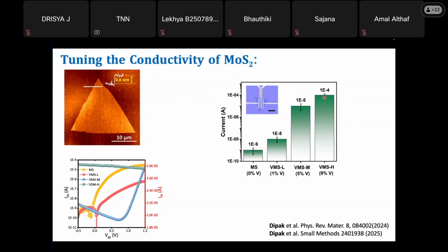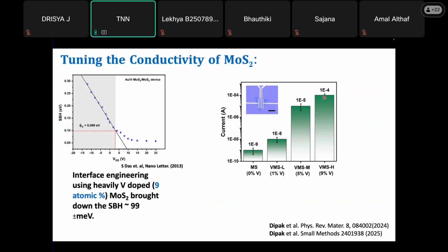Now the interesting property is that when we bring this contact to the metal-semiconductor, the MoS2-gold contact, we could bring down the barrier to approximately 99 meV. So 250 meV to 99 meV, and it's quite stable also. Even at high temperature, it's quite stable. We have done this experiment around 200 degrees Celsius. This interface is quite stable. And bringing down the barrier with these kinds of two-dimensional materials is quite interesting, and it can be really scalable.